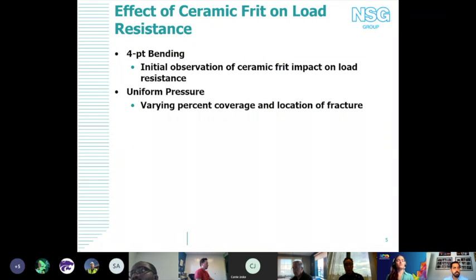So what I've done is I've just taken 2 phases of what my research was to give an idea of what this load resistance reduction looks like. Initially we did some small sample 4-point bend tests, and we use this just as an observation of, does ceramic frit impact load resistance? Does it matter which surface it's on? How much? Kind of just as a gauge of, is there an actual change in mechanical failure whenever you apply ceramic frit? And then the second, our uniform pressure test, more what you would see in terms of a 4-side simply supported piece of glass. And in this, we checked varying percentage coverage, and we're able to see where the location of failure was with regard to the frit coverage on the glass. So we'll go over both of those.